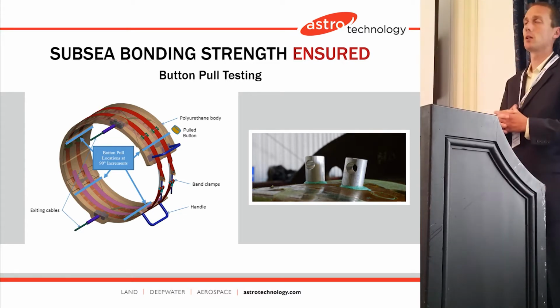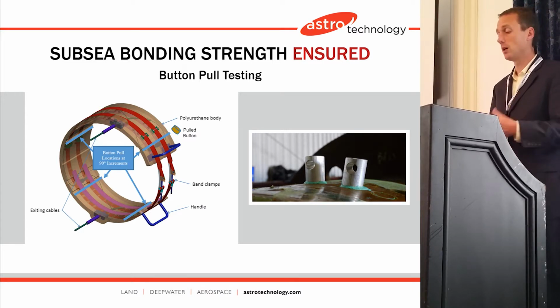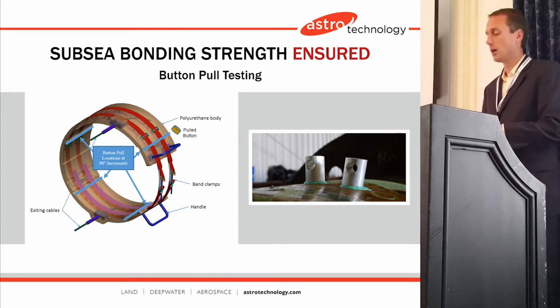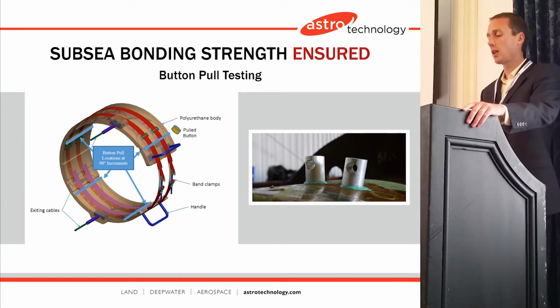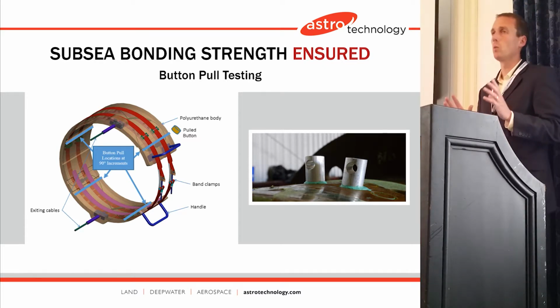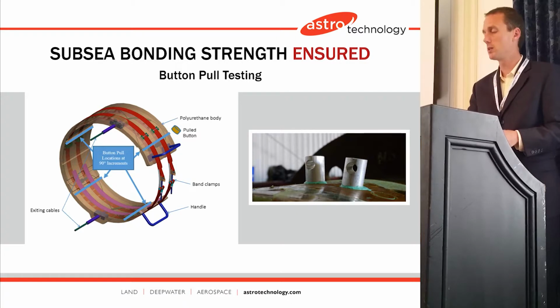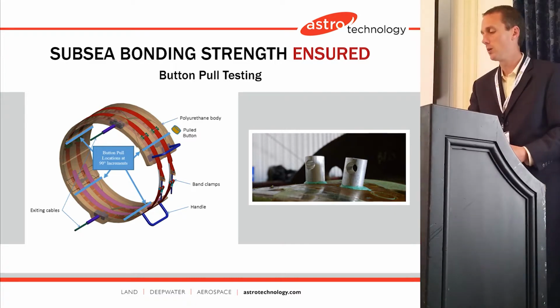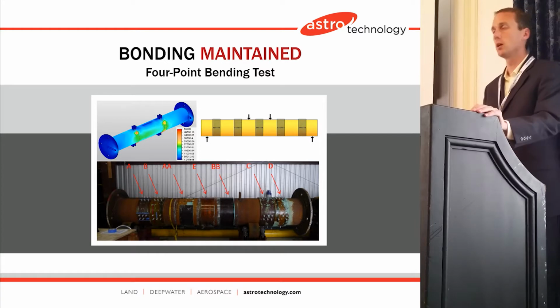And so as part of this project, we performed bonding tests with accelerated aging samples. And with these clamps, we had a number of pull buttons that we would remove after the testing, after the accelerated aging, to be able to determine the tensile strength or the yield strength of these clamps. So we used 2 methods to secure the clamps to the structure. One of those was the bands that would lock in, but also adhesive. You can see the green adhesive there on the buttons that are attached, and then those would be pulled away, and then we monitored the yield strength.